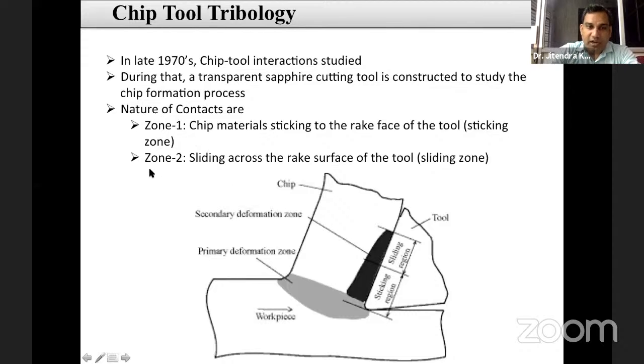Zone 1 is called the sticking zone. The chip material sticks to the rake face because of the high temperature; when it detaches from the shear plane, it has a very high temperature. Due to that high temperature, cold welding happens at the chip-tool interface, and that's why it is called a sticking zone.